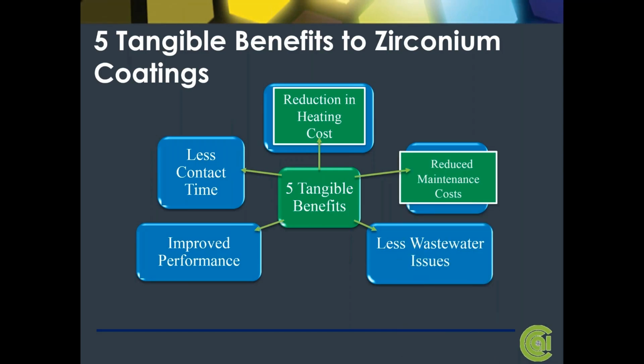Less sludge. Anybody that's running a multi-stage iron phosphate line knows that you have to go in from time to time and do maintenance on the risers and the nozzles, and go in and scrape and clean your cleaner tanks to get the buildup of sludge out. This happens with iron phosphates and zinc phosphates, but you do not have that problem with zirconium. The sludge is minimal at best.